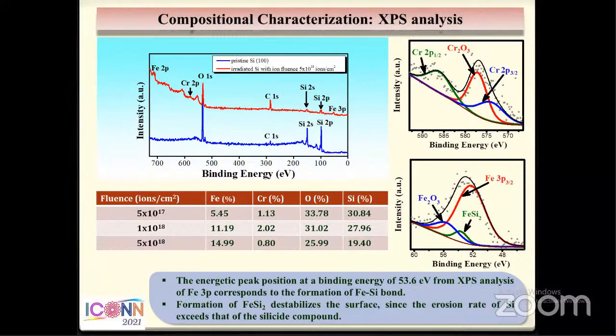So can you go to your XPS slide? Yeah, sure. In the blue and red ones, for the oxygen one, I think there is a huge difference in the intensity. What is the reason? Yeah, the reason is that the blue one is pristine silicon, but the upper one, the red one, is irradiated silicon. Irradiated means that it is bombarded by argon ions, right? So most of the native oxide layer that is present on the silicon surface is removed during bombardment. So that's why the intensity is less.